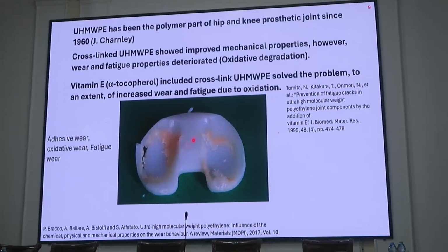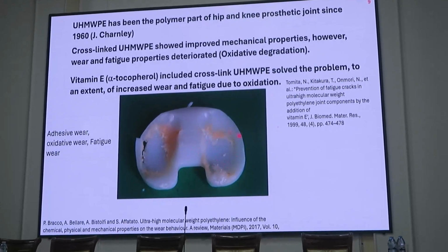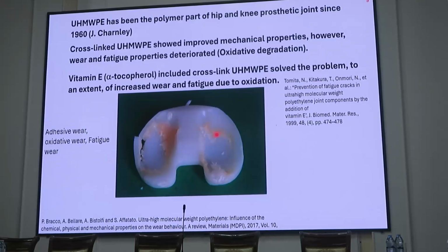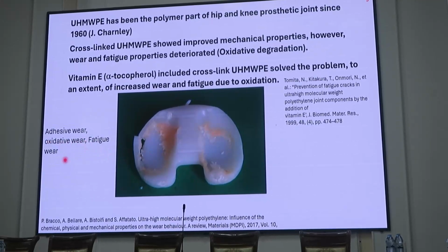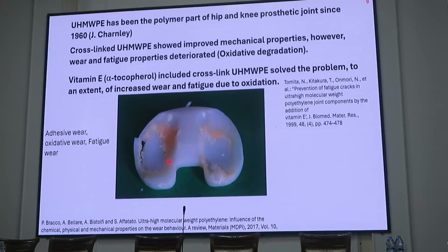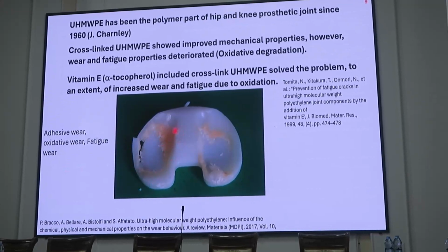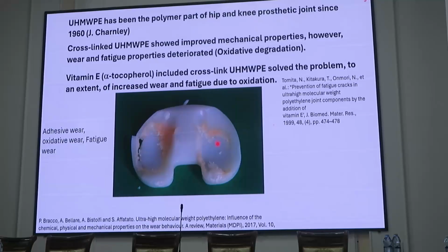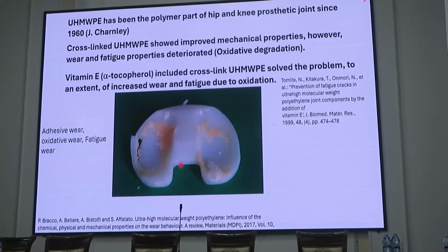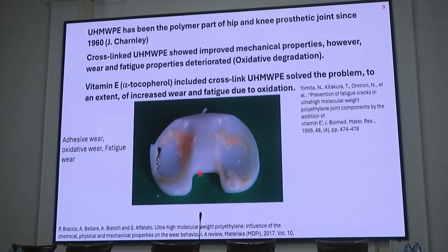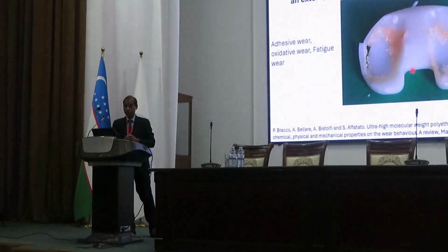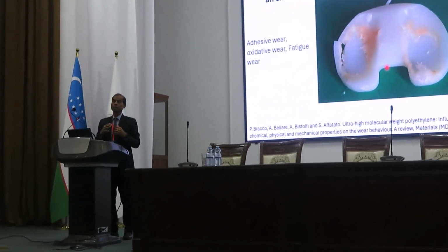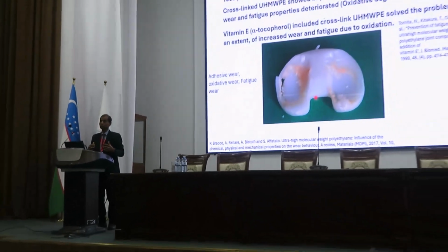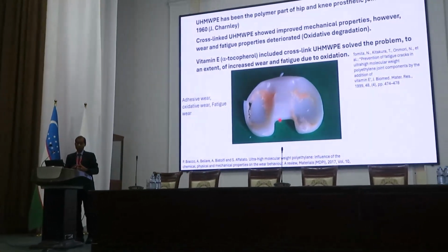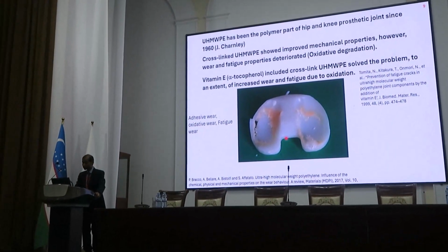This is an example of the retrieved implant from the knee, and it clearly shows the adhesive wear, oxidation wear, and fatigue wear. You can see there are a lot of broken parts here. A lot of wear has taken place. So even though the material is good and the lubrication is good, they still wear, and that's because the lubrication regime is boundary lubrication or mixed lubrication. In boundary and mixed lubrication, we know that the wear will take place.